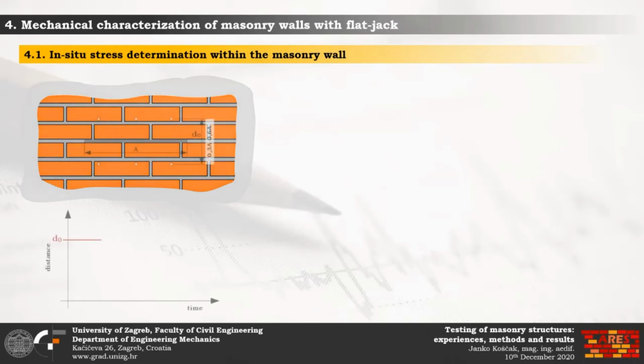The flat jack position of a width A should be marked on a selected masonry wall, and reference points for vertical distance measurement should be attached. At least 3 pairs of reference points should be placed as shown in the figure. The vertical distance between the reference points should be between 0.3 and 0.6 of the width A. Now the initial measurement D0 can be performed. After the initial measurement, the cutting of the flat jack slot is conducted, and this procedure releases the normal pressure between the reference points, so the distance between them is now of course reduced.